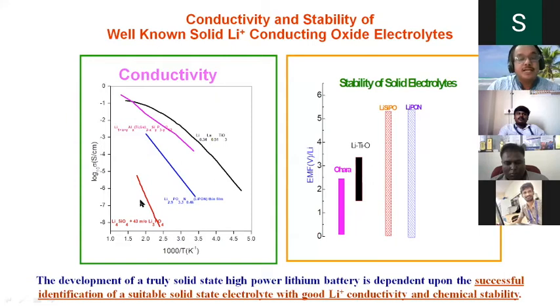So this is the conductivity map. From this conductivity, it's very clear: perovskites, lithium, lanthanum, titanate possess the maximum conductivity among the four. Next is this Ohara, lithium, titanium, aluminum phosphate made by this industry. Then Lipon, then Lisipo, with the lowest conductivity, and this lithium lanthanum titanate is the highest conductivity among the four candidates.